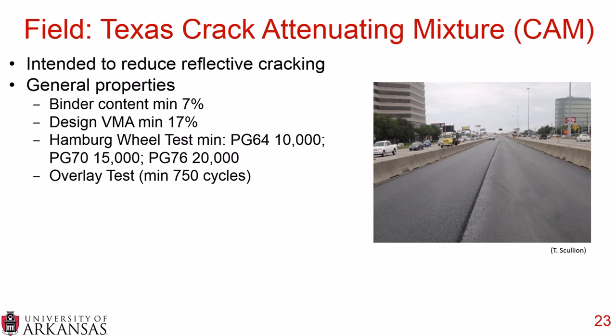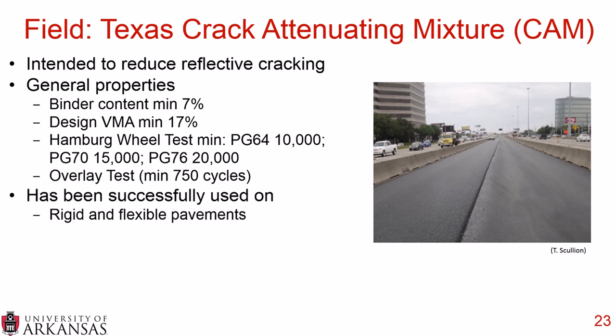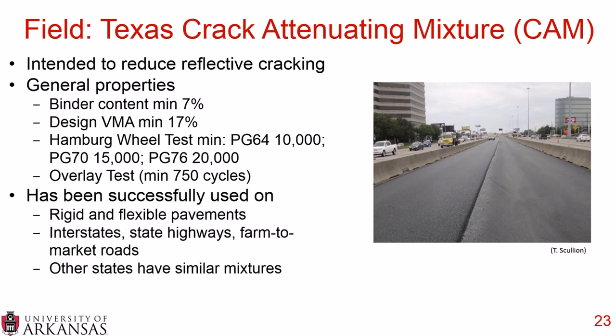The overlay test must pass a minimum of 750 cycles, and this has been highly successful on both rigid and flexible pavements. It's been placed on interstates, state highways, and farm-to-market roads. It has also motivated other states to develop similar mixtures, like you saw in the previous study in Nevada, where they have a special interlayer mixture. Texas really led the way in developing this mixture, and they have various reports available online. If you just search Texas Crack Attenuating Mixture, there are many available. Texas has all their state reports online, which is a very nice resource. You can also take a look at TxDOT Special Specification 3000, which goes over all the details for the Crack Attenuating Mixture specification.